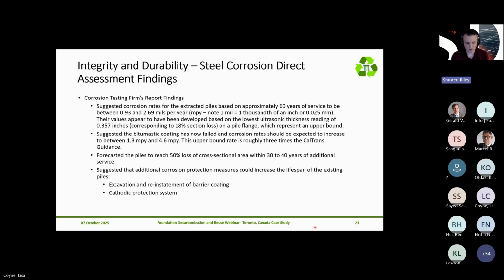So when you start to get into those sorts of numbers, making the case for pile reuse is quite difficult. So they provided a forecast, and they suggested after 30 to 40 additional years of service that the piles would be reaching 50% section loss, and provided 2 options for corrosion protection measures, which includes excavation and reinstatement of the barrier coating, and/or installation of cathodic protection, both of which would be quite costly options and might get in the way of reusing the piles.